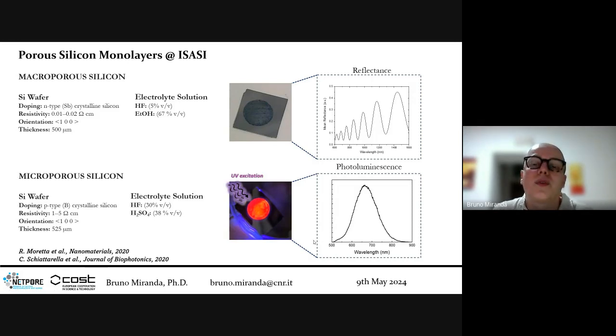With spectrofluorimetry, or also typical setups that are on the optical bench. So you need a UV laser, and you have to shine light at 90 degrees and collect the signal of the photoluminescence.